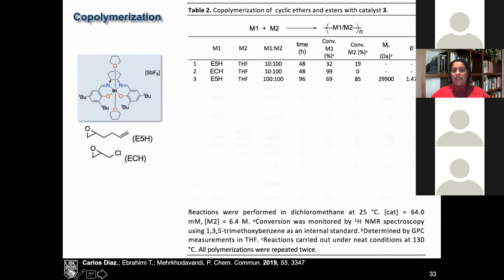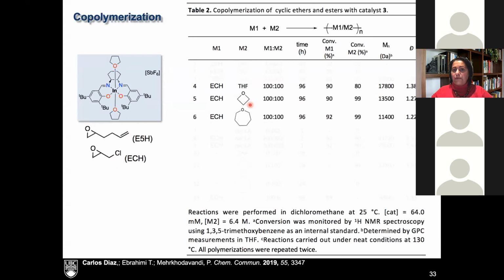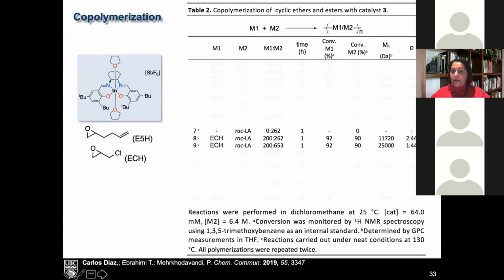Then he started looking at the copolymerization of these two epoxides, so we have a chloride or an olefin sidearm, with THF. So we can actually copolymerize tetrahydrofuran and these epoxides. He then started looking at five-membered, four-membered, and seven-membered rings in terms of oxetane and oxepane copolymerization with epichlorohydrin. We can see really high conversions for both of these, and we're forming these block copolymers in quite a controlled fashion. He was able to copolymerize these with lactide, which is really exciting for us.